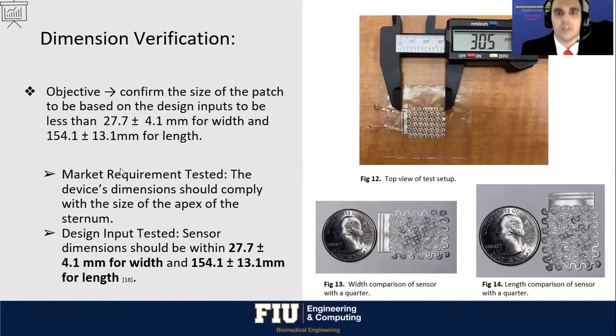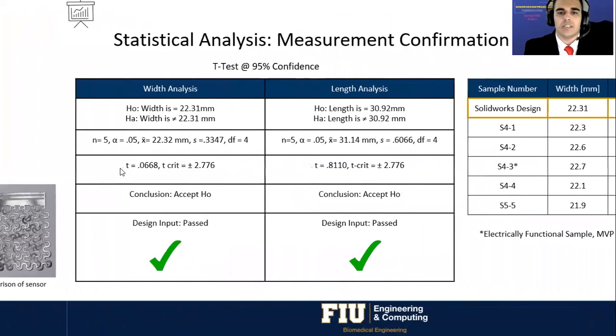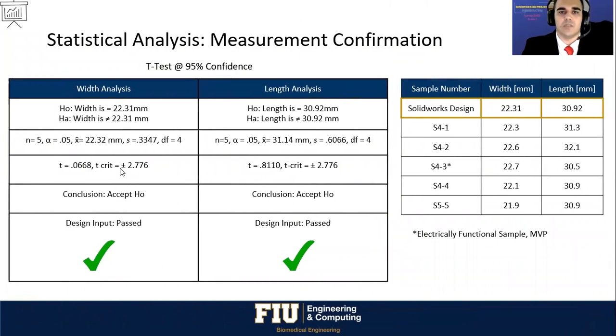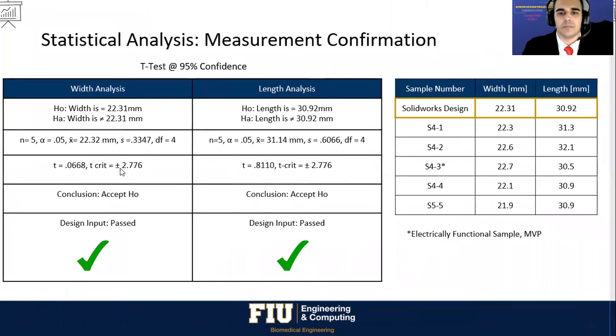Thank you, Hania. All right, so let's go over some of the verification process that we as a team were able to do. The first verification process to discuss is size confirmation of the patch. Fairly simple, but just as important as the other tests, as we did not want our sensor to be too big. Using a simple t-test with 95% confidence, we tested 5 samples that we had cut out with the desired dimensions of 22.31 by 30.92 millimeters. Our data suggests that our sample means are not significantly different, and we accept that our sensors meet the design requirements.